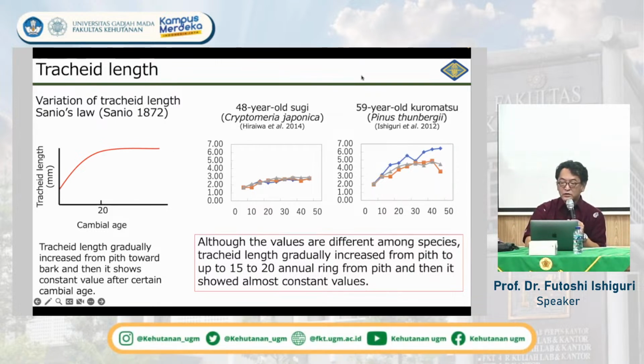So I showed it here. Again, the Japanese cedar and the pinus, the Japanese black pine. Even in the stable value, here it is about 3 millimeters, and here maybe 4 or 5 millimeters, a little bit different, but the shape, the increase and becoming stable, is the same in both species. And the start of stabilization is the same in both, around the 20th annual ring from the pith. So the value itself is sometimes different, but the trend is the same.